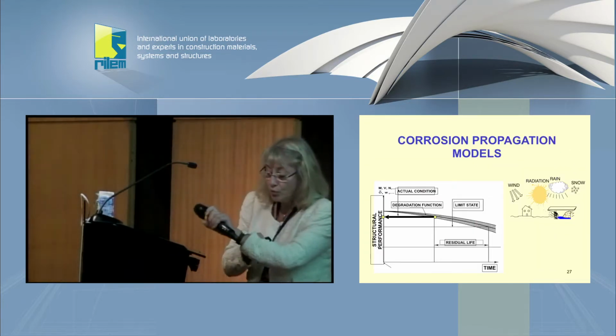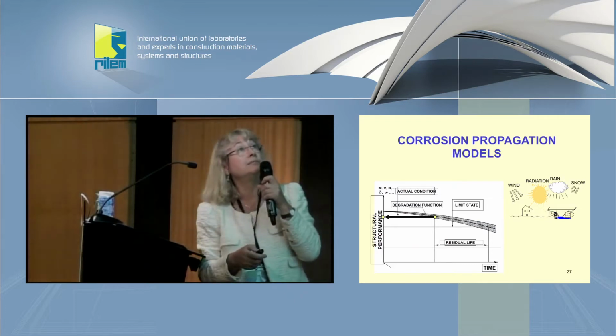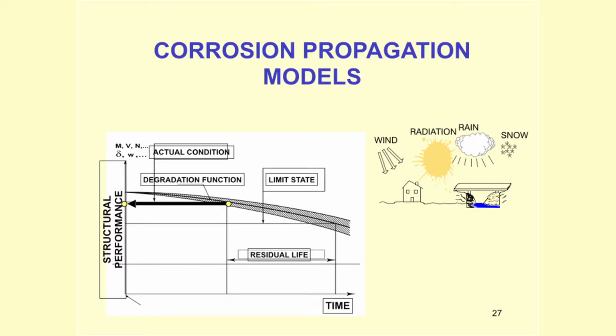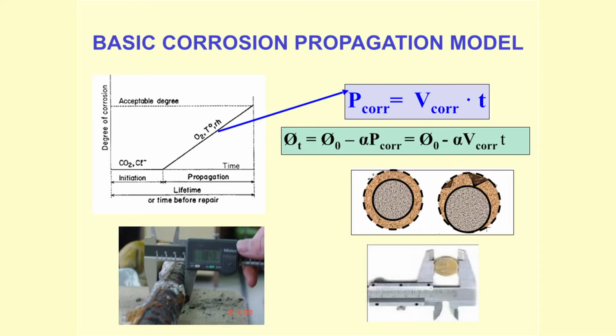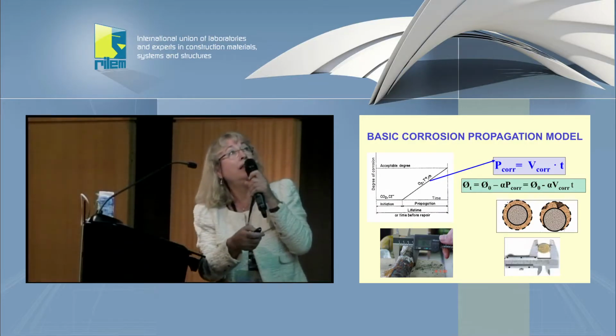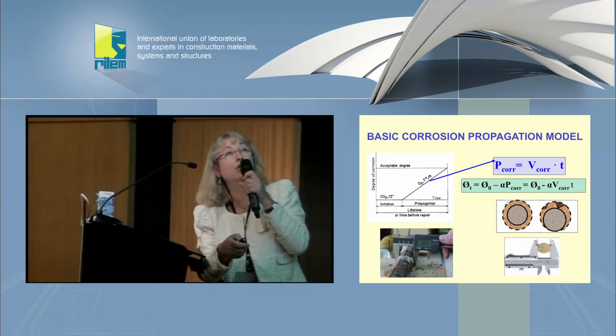Well, I go now to end with the propagation models. Again, we need to try to develop a damage model for the propagation of the corrosion, also taking into account the effect of the environment. The model was published some time ago and is very simple. The amount of corrosion reached after a certain time depends on the velocity of corrosion, the corrosion rate. I mean, millimeters per year of penetration of the corrosion multiplied by the years give the millimeters after this time.